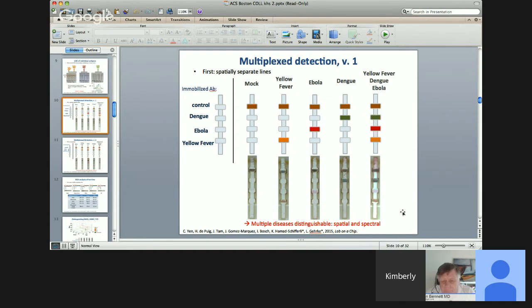Okay, so these are the results of those experiments. We can see that if we run yellow fever, we get a hit here, but not here and here, and it's an orange band. For Ebola, we get a red band here, but nothing else here and here. Same for dengue, we get a green band here, but not here and here. And then finally, if all three are present, we get hits at all positions, and they're all the correct colors.